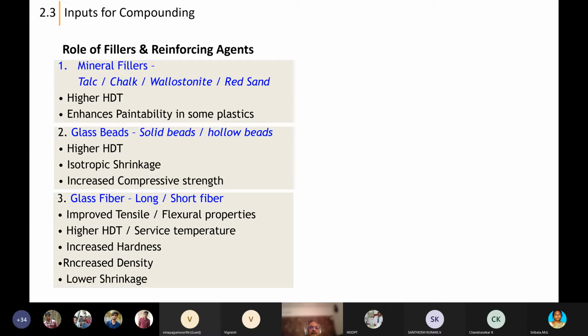The other major fiber is glass fiber. Glass fiber again has long and short fiber. They give you massive improvement in tensile and flexural properties. They give you higher HDT and service temperature. See, normal nylon 6 has a service temperature of around 70 degrees. You continuously expose it to 70 degrees, over time, the properties will drop. But when you add 30% of glass fiber, the service temperature will jump to 120.